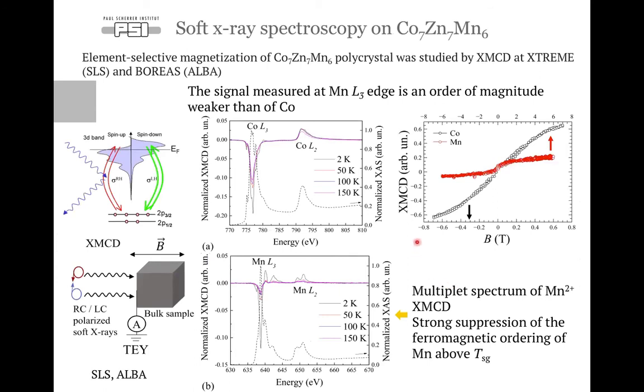Next, we have also performed soft X-ray spectroscopy experiments on Co7Zn7Mn6 samples. We used polycrystalline ingots synthesized in the same way as single crystals, and studied them by circularly polarized soft X-rays at the XTREME and BOREAS beamlines at the Swiss Light Source and ALBA synchrotrons respectively. With XMCD, we directly probe the 2p to 3d transition to probe the magnetism with element selectivity at the cobalt side and the manganese side. What we can see in the Co7Zn7Mn6 material is that the XMCD signal from cobalt is quite large. It's about 10 or 20% of the total absorption, which is reasonable for metallic cobalt.